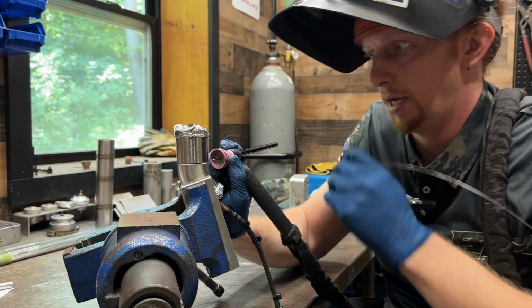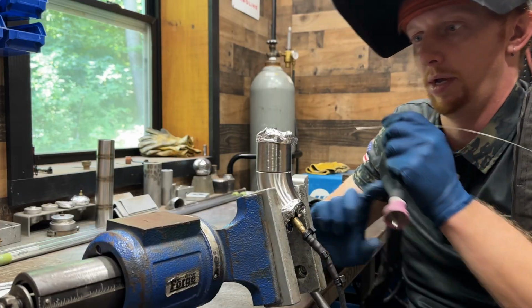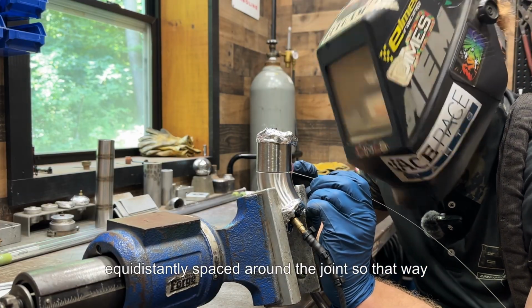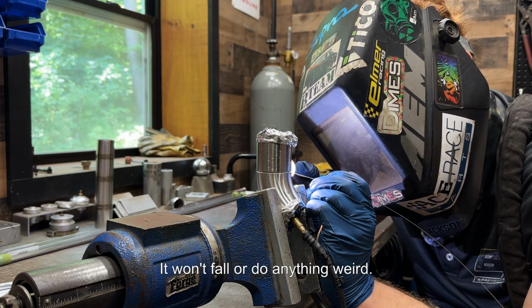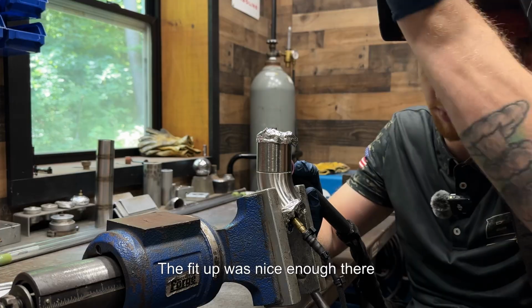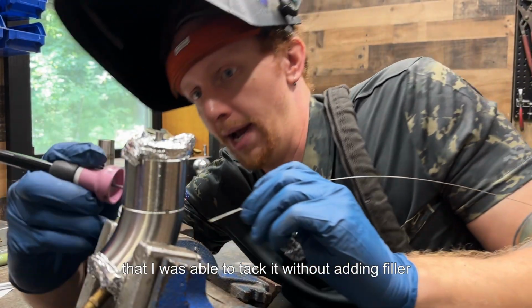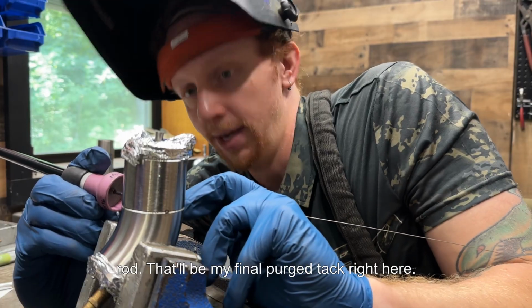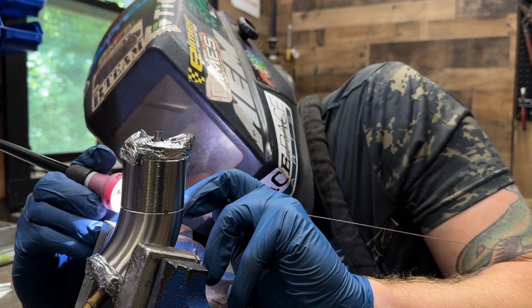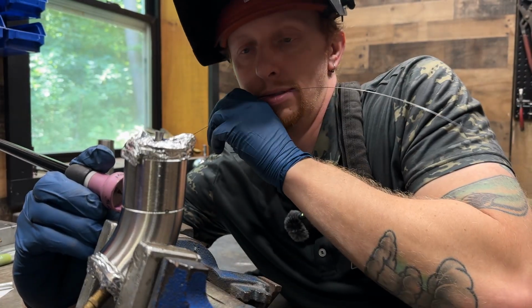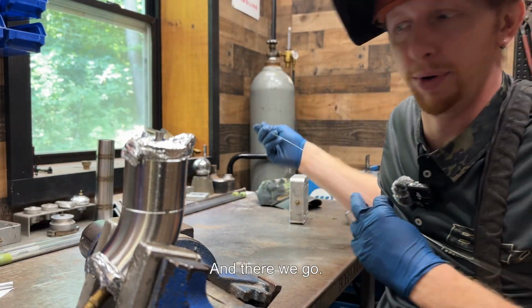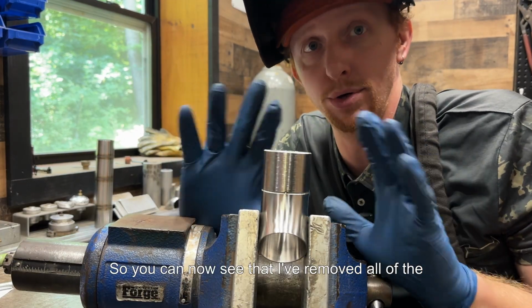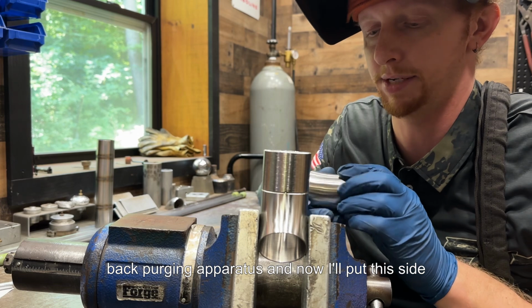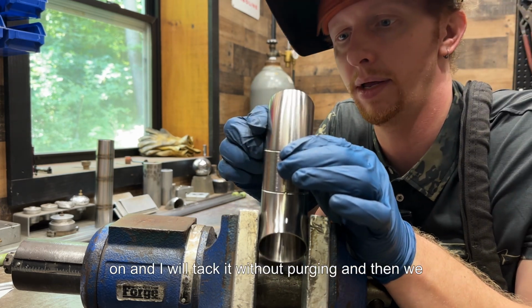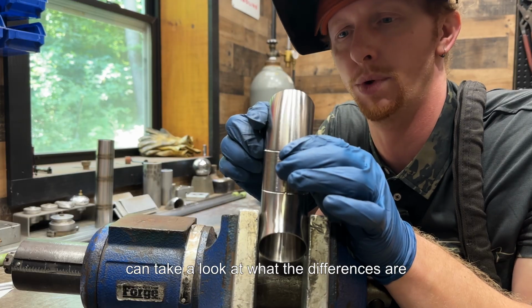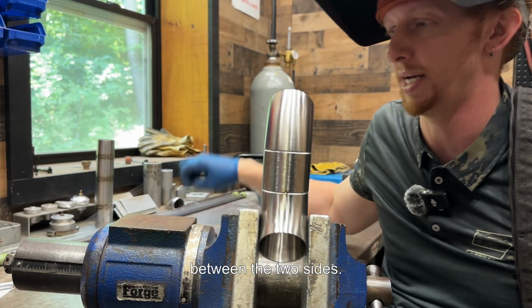There's a tack there, and I'll tack this in 4 places, equidistantly spaced around the joint, so that way it won't fall or do anything weird. The setup was nice enough there that I was able to tack it without adding filler rod. And that'll be my final purge tack right here. And there we go. So you can now see that I've removed all of the back purging apparatus. And now I'll put this side on and I will tack it without purging. And then we can take a look at what the differences are between the 2 sides.